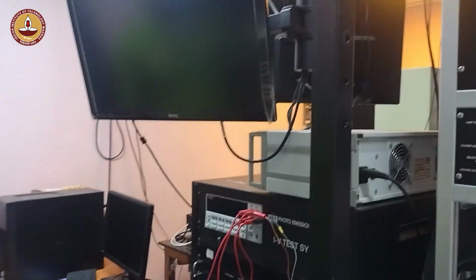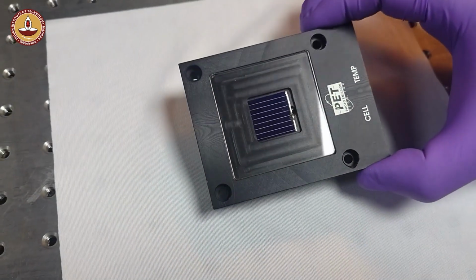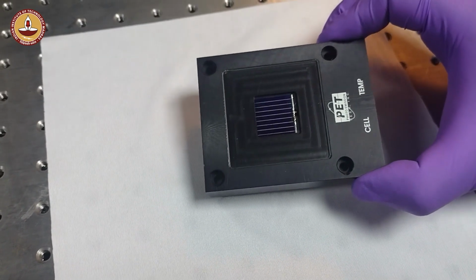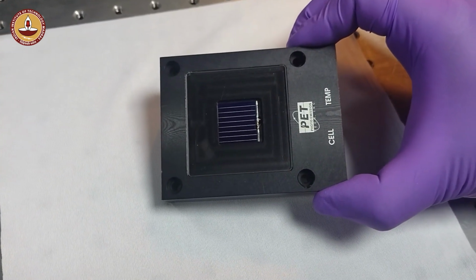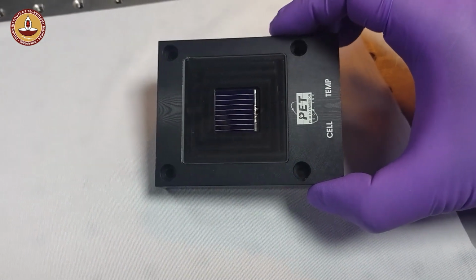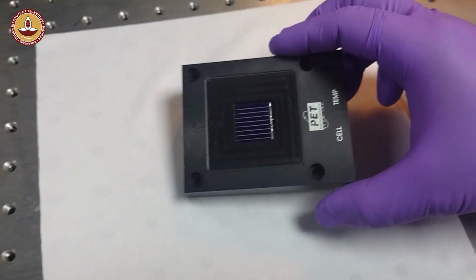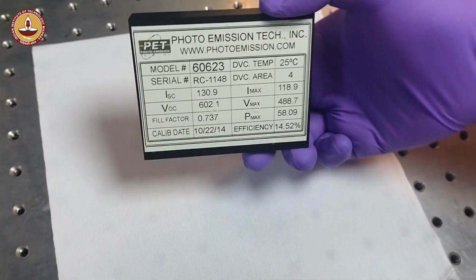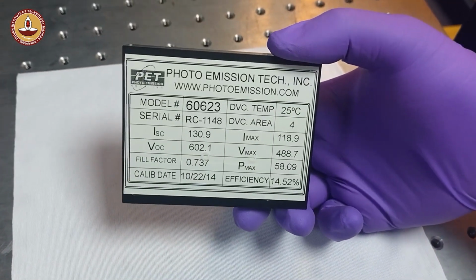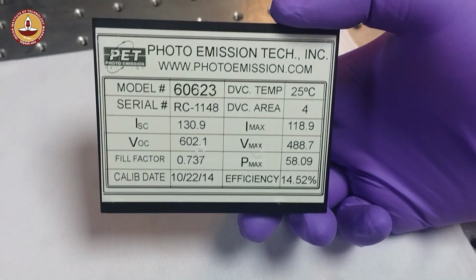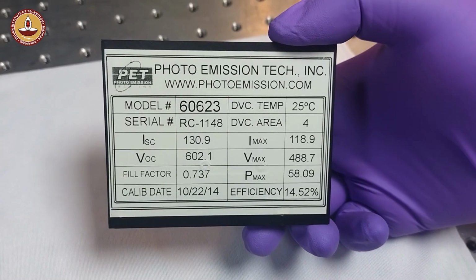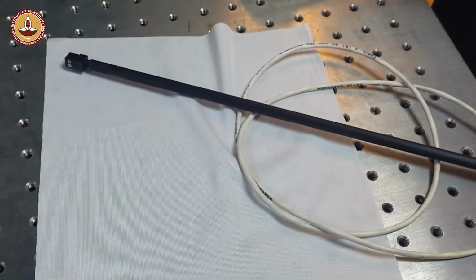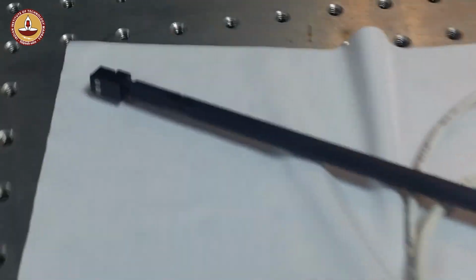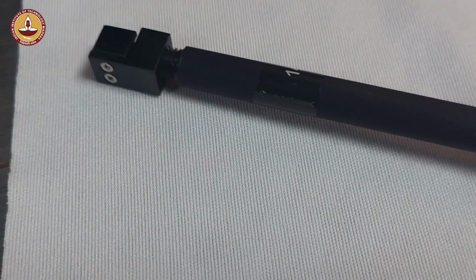Before starting the measurement, the solar simulator is calibrated using a standard silicon solar cell, certified by NREL. Under standard testing conditions, the reference cell produces a short circuit current of 130.9 milliamps and an open circuit voltage of 602.1 millivolt for an active area of 4 cm². Other measurement results are displayed on the screen. This standard cell is used for calibrating the intensity of the light to 100 milliwatt per cm². To further confirm the calibration, we use a photodetector provided by the manufacturer, which provides 14.3 millivolt under 1 sun illumination.